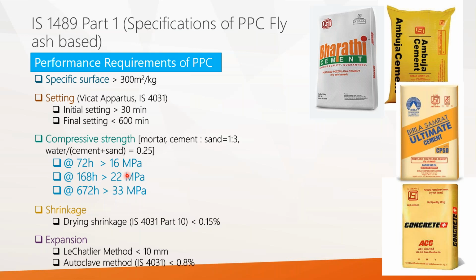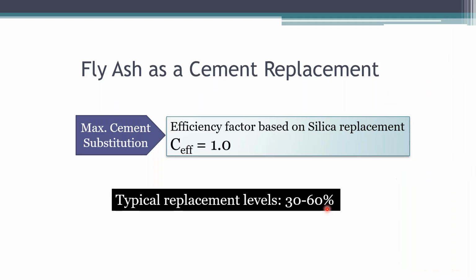Now, of course, in India today, we are making a lot of PPC. Almost, like I said, 70% of our cement consumption is primarily in the form of PPC. Different companies are already making it. But if you look at the Indian code for PPC, the requirements are primarily that of the 33 grade of cement. That is what is currently prescribed. That is what is expected from a PPC. Now, that is partly because the gradation of the cement or the grade of cement is based on the 28-day strength. And because it's a slower reacting material, the higher strength, ultimate strength, is achieved at a much later time.